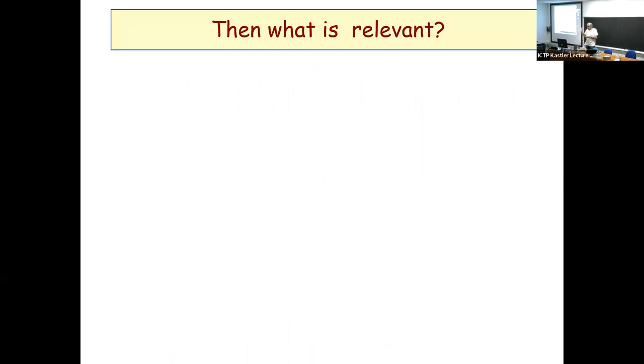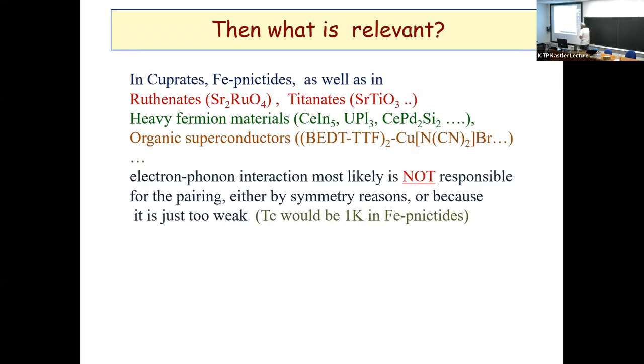And with this, I will say a phrase that not everyone agrees with. That in cuprates, iron pnictides, ruthenates, titanates, heavy fermion materials, organic superconductors, I am willing to put twisted bilayer graphene there, but I know that this is not a solved problem, electron-phonon interaction is not responsible for the pairing by one reason or another. In each case, you need to state the reason. Either by symmetry, it doesn't give the right symmetry of the order state, or because it's weak.